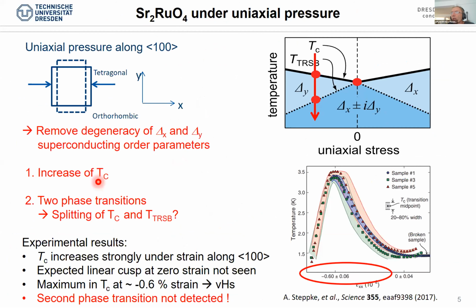And of course, we know that this was the expectation. We have an increase of Tc, but on the other hand, the second order parameter is suppressed. So the onset of the coherent state should be at a lower temperature. There should be a second transition into the time reversal symmetry breaking state at applied uniaxial stress. And this was something we wanted to measure with muons, because so far the time reversal symmetry breaking in these systems has only been seen by muons and by the Kerr rotation effects.